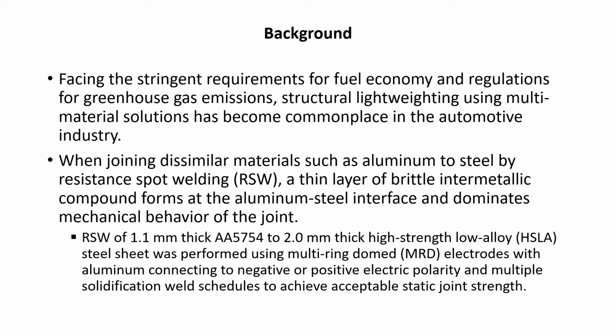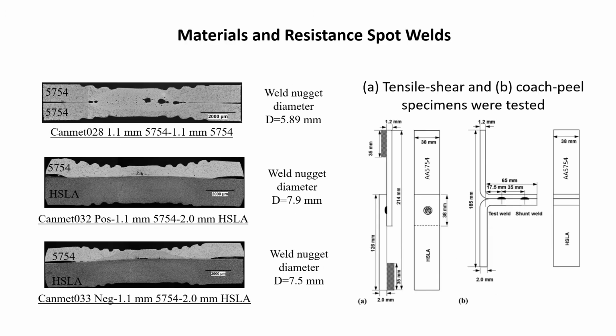So in the present work, we welded 1.1 mm thick AA5754 aluminum alloy to 2 mm thick high-strength low-alloy steel sheets using multi-domed electrodes, with aluminum connecting to negative or positive electric polarity and multiple solidification weld schedules to achieve acceptable static joint strength. Tensile shear and coach peel specimens were welded and tested.